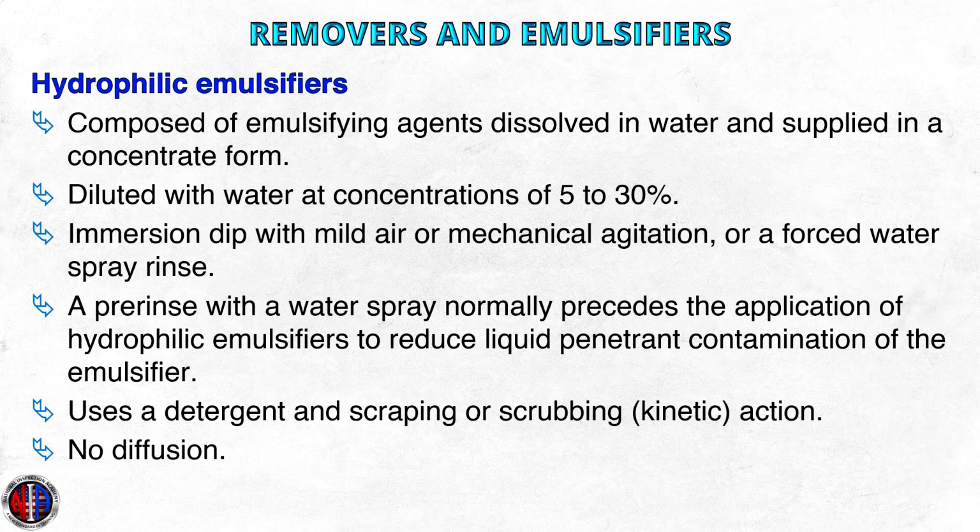The term hydrophilic can be defined as having an affinity for water, whereas lipophilic means having an affinity for oil. Hydrophilic emulsifiers function through a detergent and scraping or scrubbing action. Diffusion does not take place in this mechanism of action.